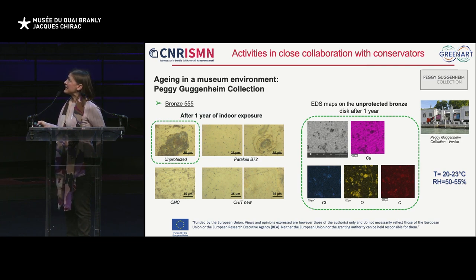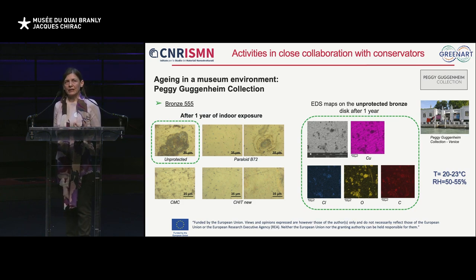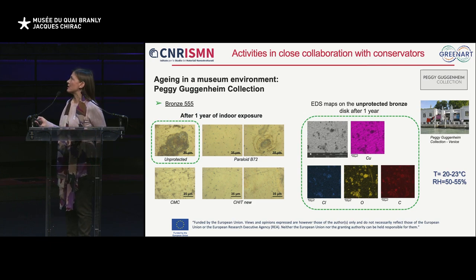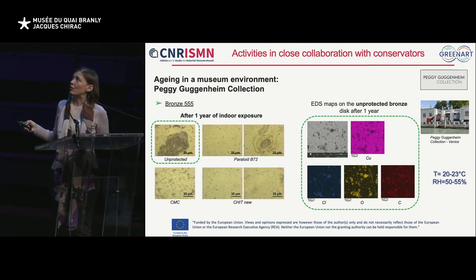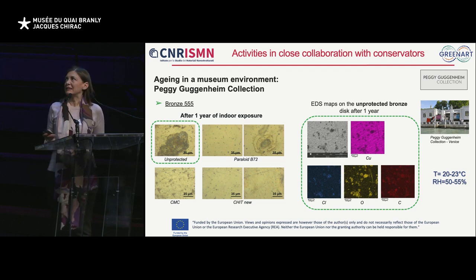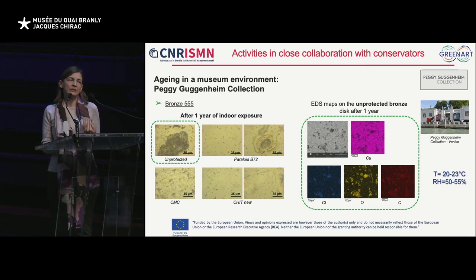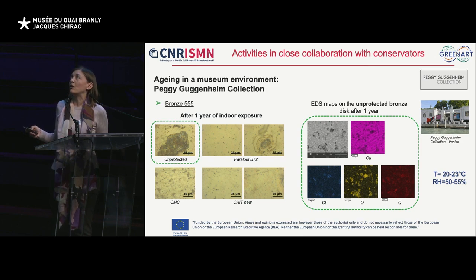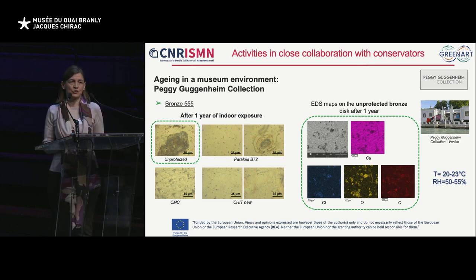And here you can see the results of EDS analysis, which can provide the elemental composition on the surface of the mock-up. And we can observe, for example, by looking at the distribution of copper and oxygen, the presence of cuprite, but also the presence of chloride. So it means that after 1 year of treatment inside the museum, if we don't have a protective coating, we can already observe the formation of degradation products.